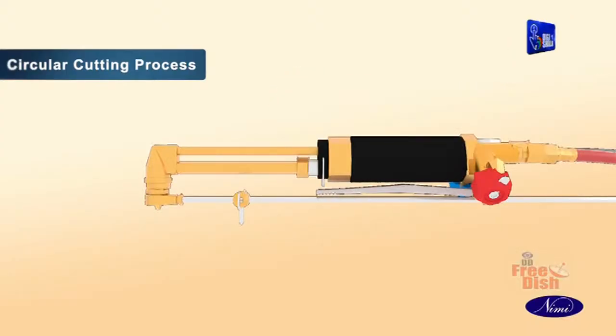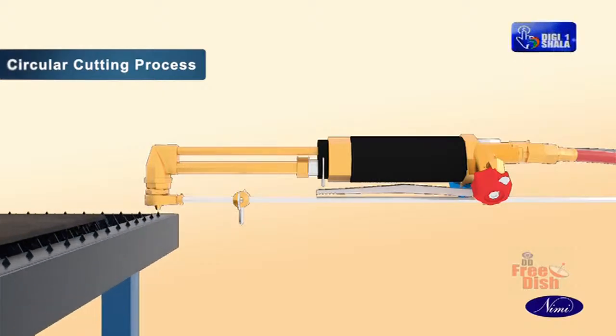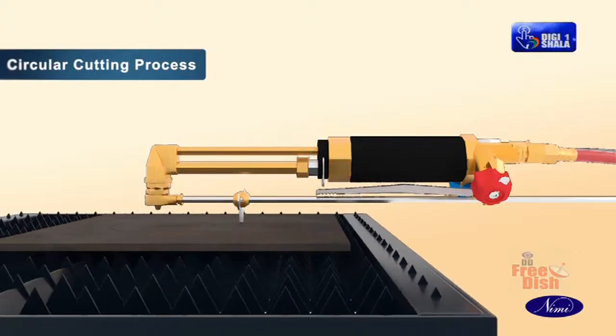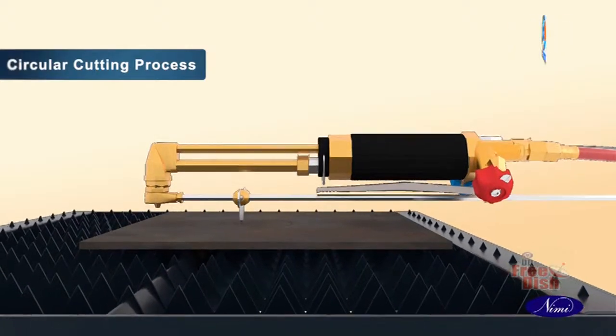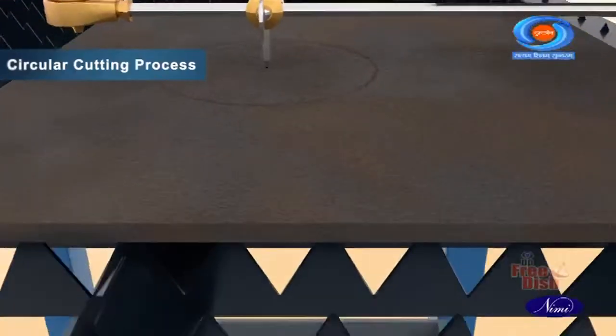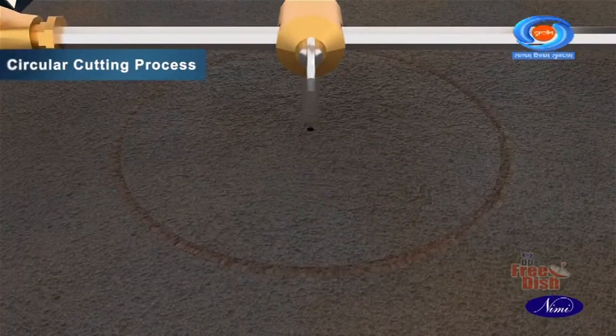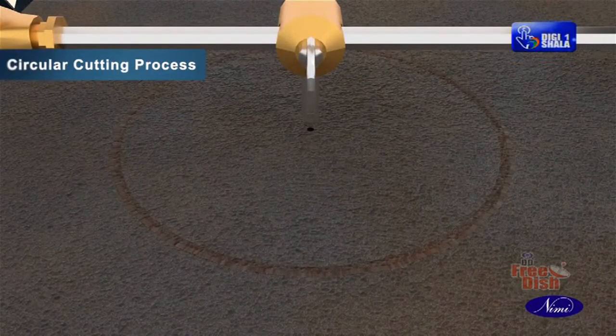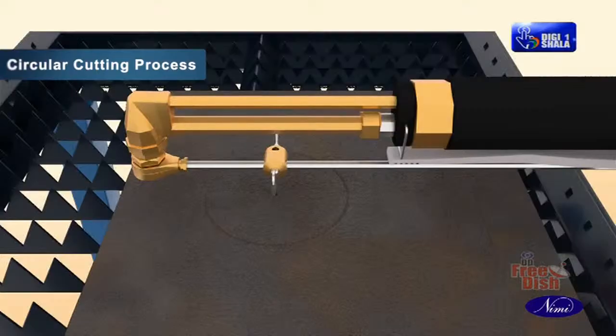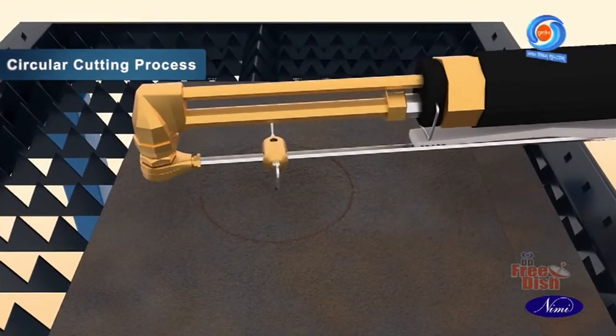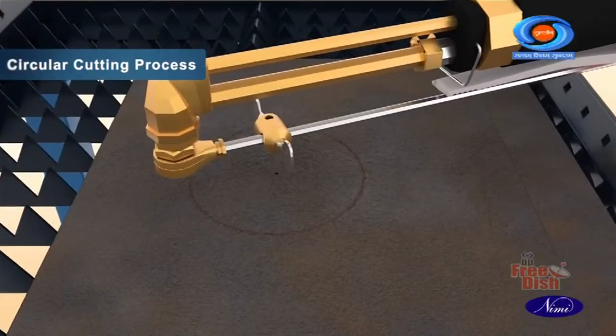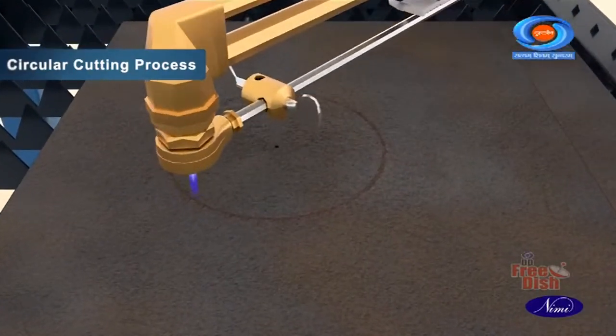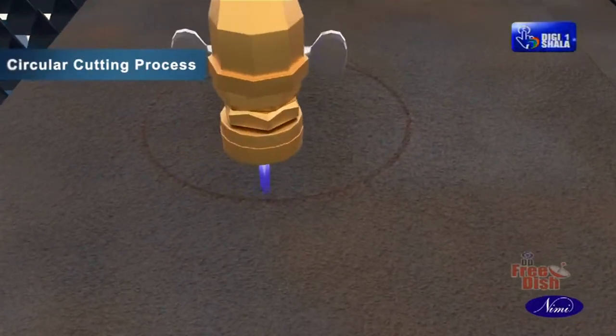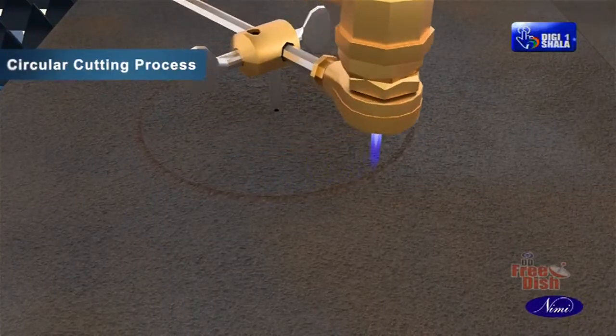When the plate becomes red hot, open the stream of cutting oxygen and cut the circle. For cutting a circle, attach a cutting torch nozzle to the pivot block and follow the same method used to cut a straight line and bevel. It is important to pierce a small hole inside the circumference of the circle to be cut, then move the torch to the nearest point on the circumference, and use the pivot block to move the flame along the circumference of the circle.